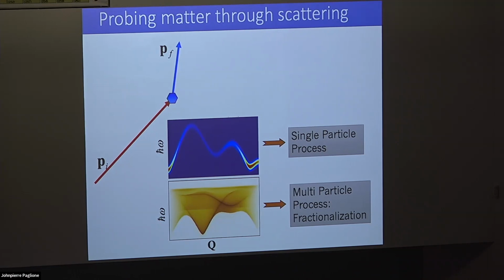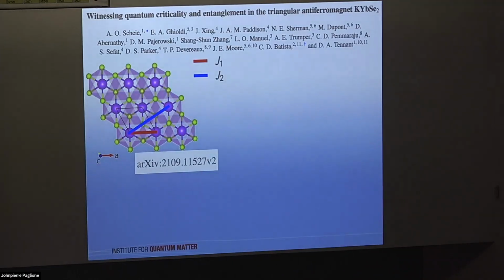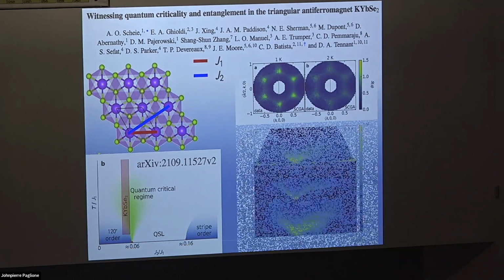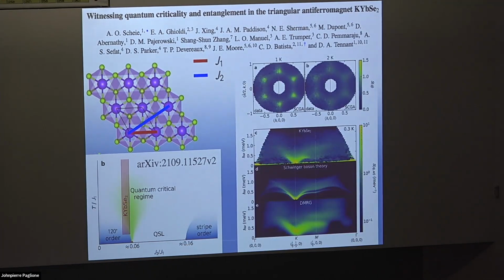So, for example, in this work, I think a very important challenge in work on these compounds is really understanding how well ordered these actually are, crystallographically. Is it really a properly ordered structure? Because any disorder could actually lead to these kinds of broadenings, even without interesting collective spin-liquid-like physics. So that's really the key challenge to address, and it makes it all exciting.